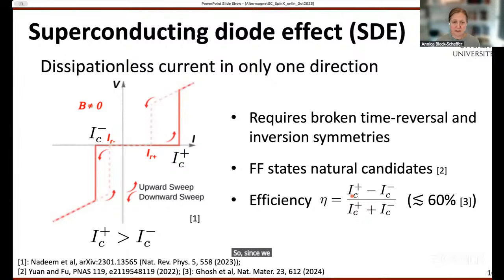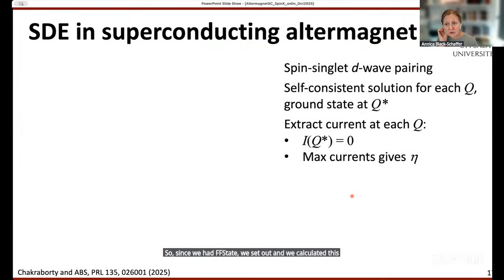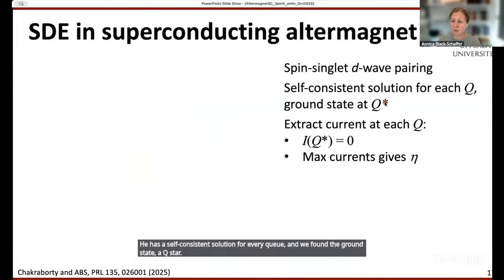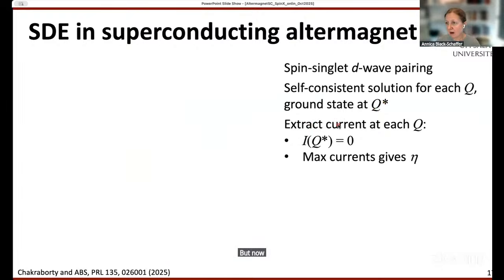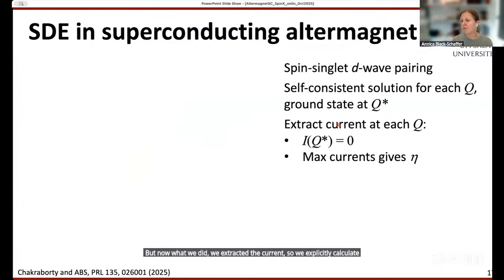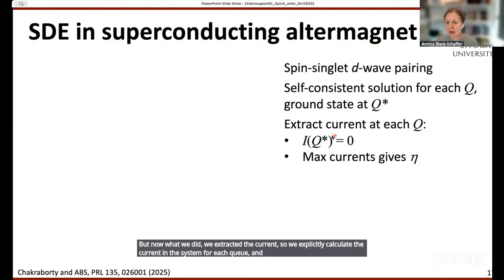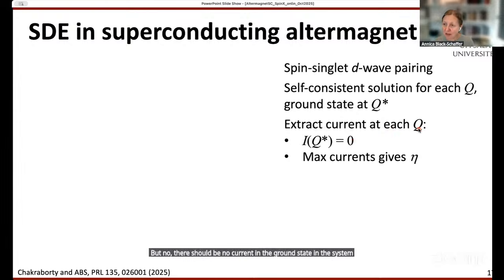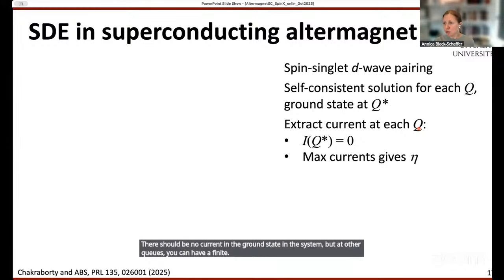So since we had the FF state, we set out and calculated this effect. Just to repeat what we did, we started with the spin singlet d-wave pairing, because that's what we needed. We had a self-consistent solution for every Q, and we found a ground state, a Q star. That's exactly what we did before. But now we extracted the current. So we explicitly calculate the current in the system for each Q. The current in the ground state needs to be zero. There should be no current in the ground state. But at other Qs, you can have a finite current. Effectively, it's the Q that drives the current in the system. And the maximum current I will have in either direction, positive and negative, will give you this efficiency.